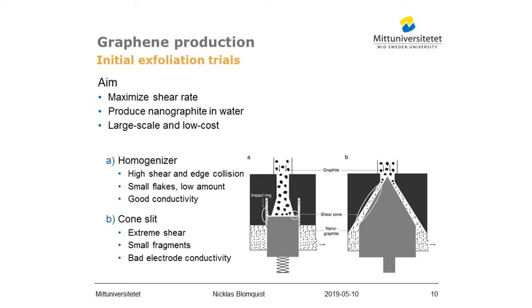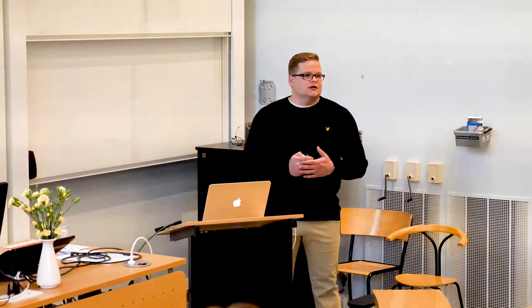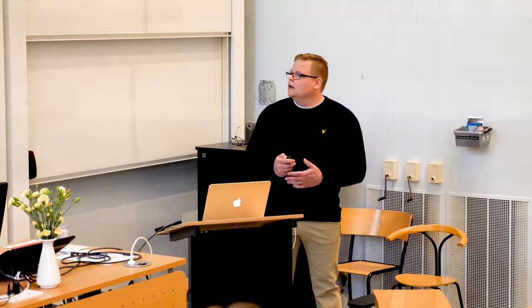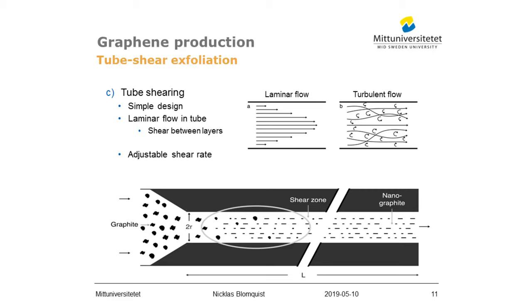Unfortunately, this shear zone gave rise to an extreme shear. So the flakes were just small fragments, and the conductivity when we made electrodes was really low. We then decided to simplify the shear zone as much as possible, also to understand what's actually happening inside the shear zone. And then I designed a tube shear system based on laminar shear in tubes.